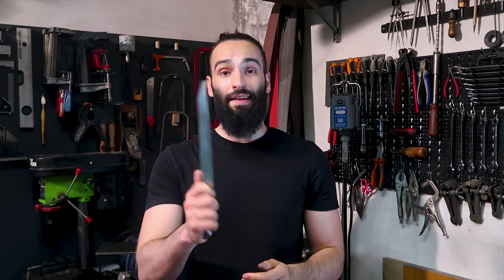And here you have it! Both blades are now heat treated and ready for handles. Even though both came out hard enough, I think I won't ever try again to heat treat stainless in oil, and there are two main reasons for that. The first is that taking off the foil from the blade before oil quenching took a really long time and the blade cooled off. That has to be the main reason why the oil one is not as hard as the plate quenched one. The other reason is that the one I quenched in oil had a real huge bend in it. I was able to take off most of it in tempering, but I would prefer to not have to deal with it. The one that I plate quenched was completely straight.